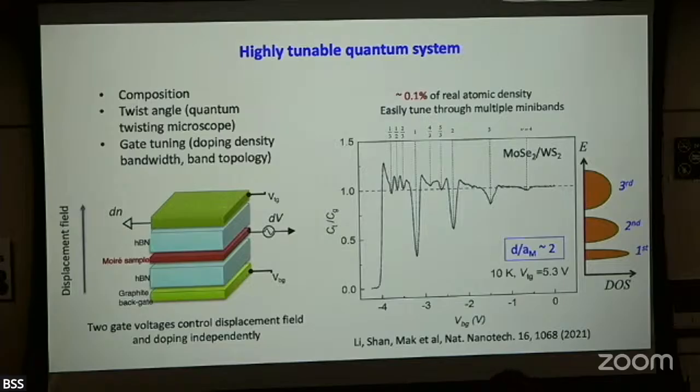And for small density, you always get into the regime where the separation between the charges actually is bigger than the separation from your sample to your metallic top gate, right? And in that case, you have to think about the effect of image charge. So at low density, you don't just have charge in your sample, you have image charge. It's like an exciton. So this interaction actually will change a lot. And that's the major contribution of this background.